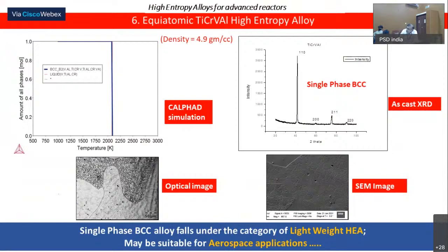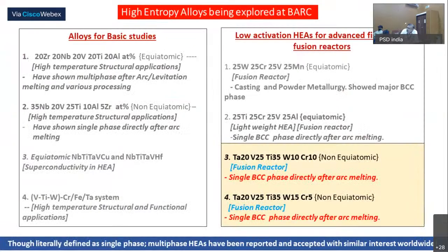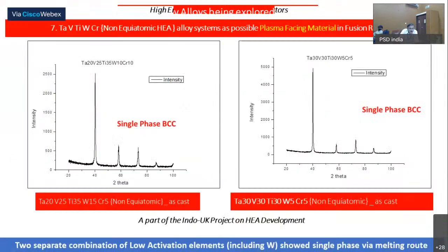My collaborator was not ready to share more than this because they feel that it has some potential for application. So I had to move to the other alloy system now, and I am showing some for advanced reactors, some of the single phase material we have found, which have low activation elements present, and they remain single phase all along. And that is where I wanted to share some of the work, on how to use positron annihilation to figure out where the strain is and where the defects are generated. So we have already done some irradiation experiments to generate a lot of irradiation induced defects, and that will come to the positron lab for generating their curves to figure out how much defect we have in the materials.